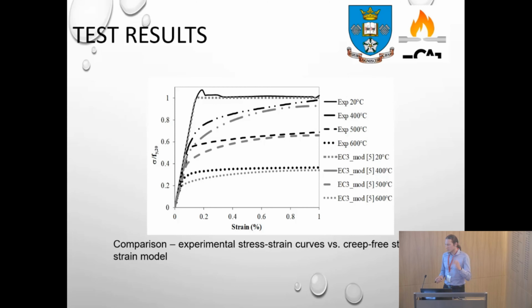We started with the 1% Eurocode modified model as a possible representation of a creep-free model. We did some stress rate tests on the coupons quite fast, 10 megapascals per minute. So we tried to compare those stress strain tests with our model. This is the comparison with the modified Eurocode 1% strain model, which by our definition should represent a creep-free stress strain model. You can see that the results are not that far from each other, so that 1% could be used as a representation.